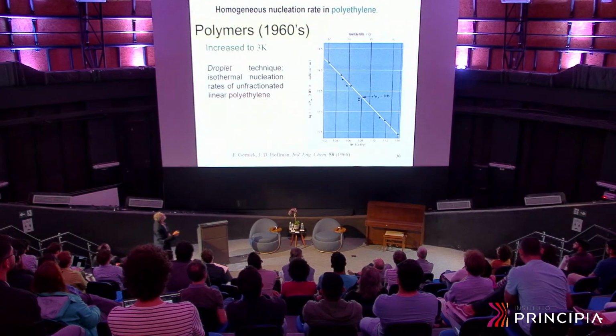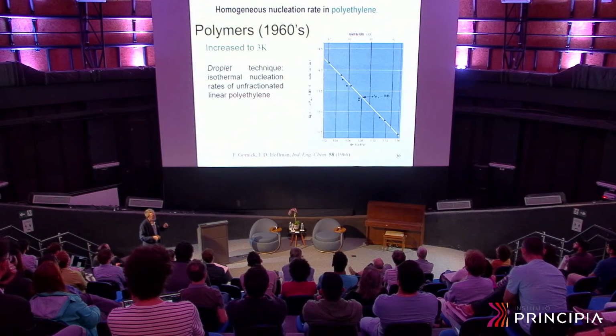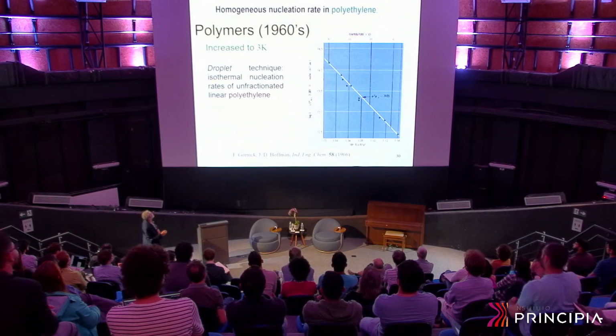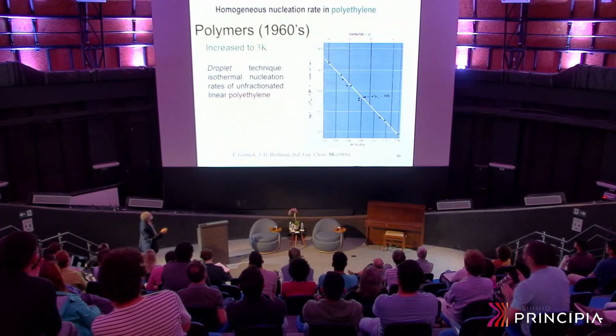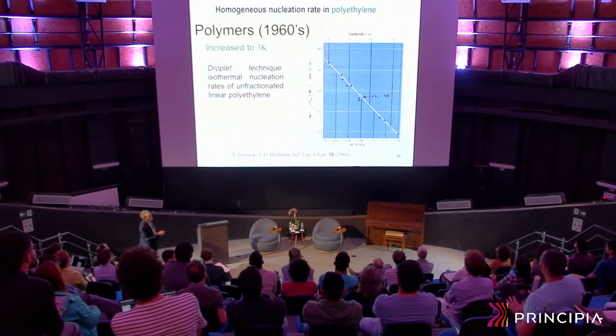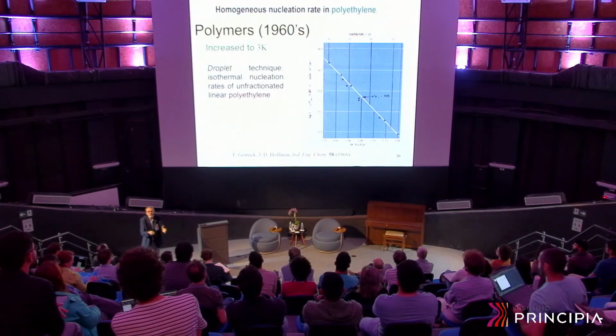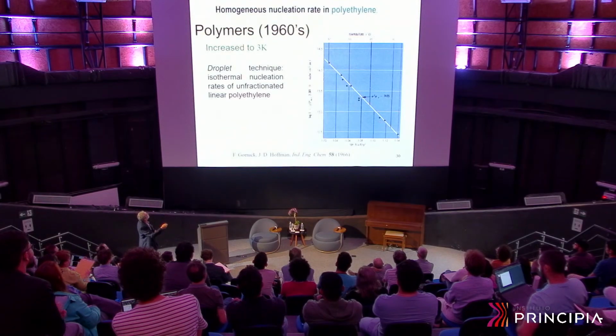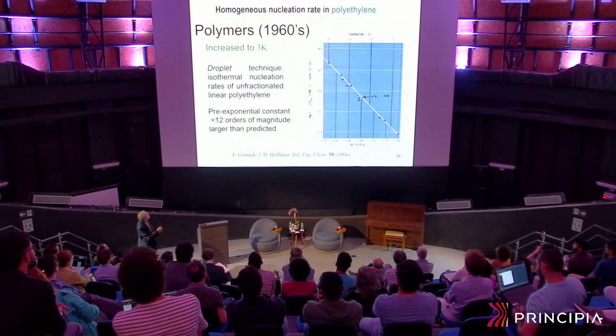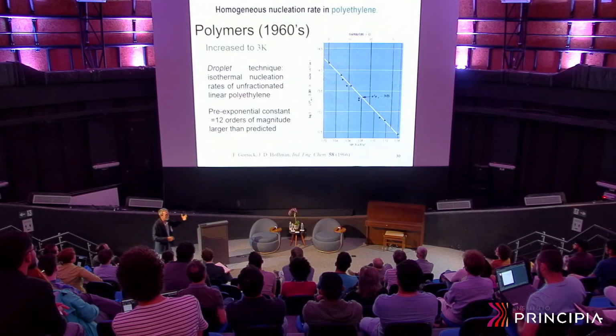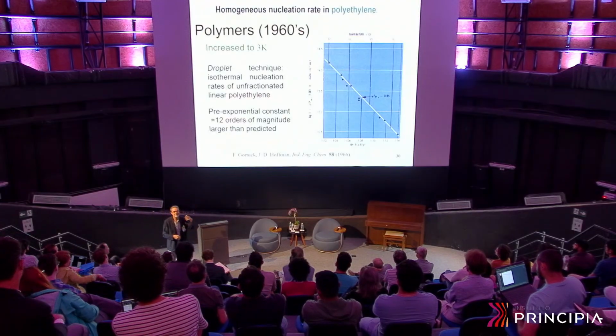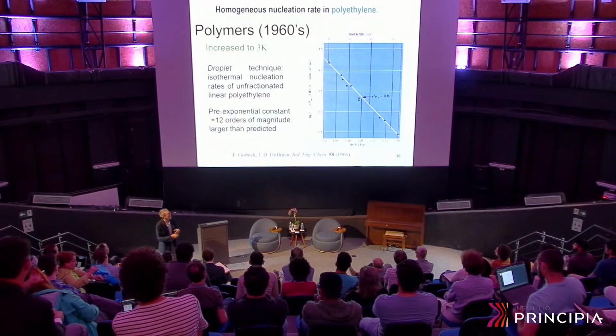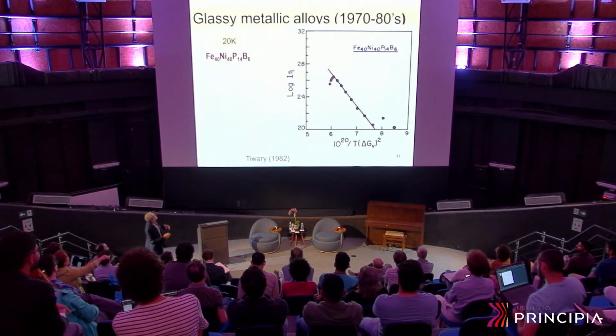Ten years later, John Hoffman, then at the National Bureau of Standards, was able to measure nucleation rates in a polymer, polyethylene. 3 degrees Kelvin. Well, 3 degrees Kelvin is better than 2, 50% better. Nice straight line, extrapolated. Guess what? The discrepancy went up to 12 orders of magnitude. 3 degrees Kelvin is not a good test. Somebody else has to measure in a better way.